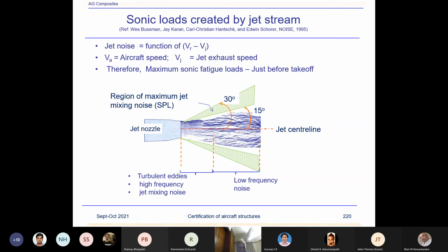Sorry for that. Thanks. Okay, now as I was saying, this is the jet exhaust, and the maximum noise usually occurs in these areas, 15 to 30 degrees from the jet center line. And jet noise is a function of VJ minus VA, where VA is the aircraft speed and VJ is the jet exhaust speed. The aircraft speed at that time is low, and the jet exhaust speed is high. Therefore, the maximum sonic fatigue load will occur just before takeoff, because jet thrust is very high at that time. And this lasts only for about a minute or so, usually.